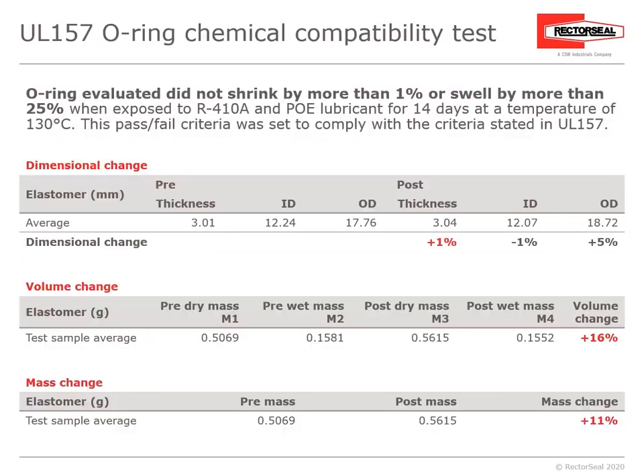Let's talk about each of these UL certifications. The UL 157 is an O-ring chemical compatibility test, and that is that the O-ring evaluated should not shrink by more than 1% or swell more than 25% when exposed to R410A and POE lubricant for 14 days at a temperature of 130 degrees Celsius or 266 degrees Fahrenheit. This pass-fail criteria was set to comply with the criteria stated in UL 157. You can see the dimensional change at 1%, volume change at plus 16%, and the mass change at only 11%.